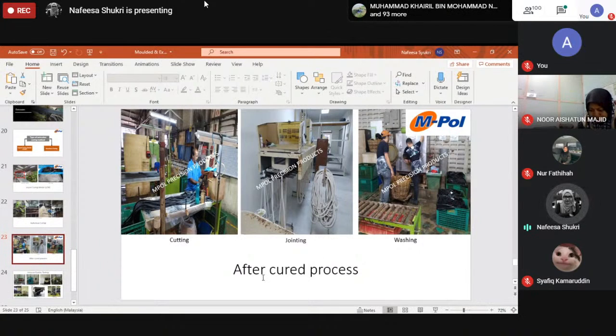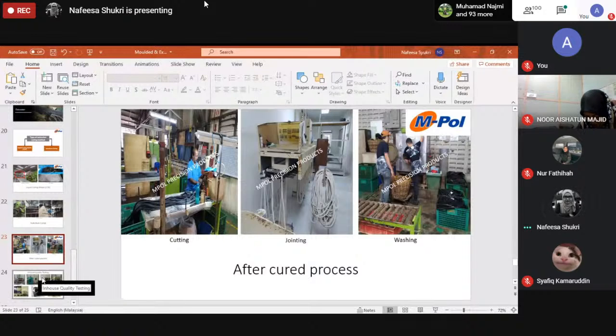We also have washing for autoclave. For example, as I mentioned before, we apply the powder for the uncured rubber process. So after curing, the powder will also be attached on the surface of the rubber tubing. So the washing process is needed in order to remove this powder from the rubber tubing surface or rubber hoses surface.